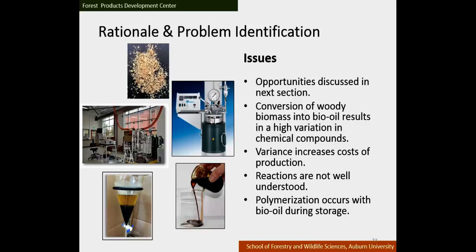So what are some of the issues that we've discovered with this? These are well-known issues in the literature, so it's not like we really discovered this. But one of the issues with bio-oil is that it will polymerize as it sits. So if a manufacturer has a bucket of bio-oil, so to speak, if you let it sit there for time, it'll slowly react and polymerize, and it will thicken. So the viscosity will increase, and so it's not stable, but it's dynamic, and so that can be a challenge, because if you're going to use bio-oil as a feedstock for adhesives, you want something that's consistent. And that's another challenge, is it's not consistent.